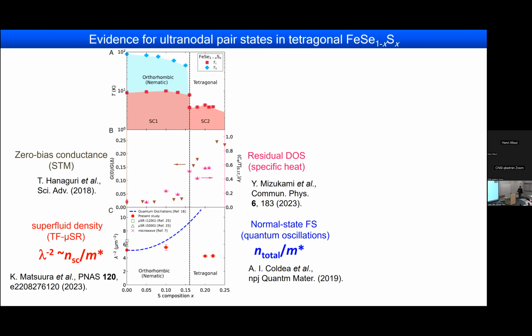And as you can see, if you go into the SC2 phase, you can see big deviations. So this means that a very large number of electrons remain normal, which is consistent with the presence of some kind of Fermi surface left inside the superconducting state.